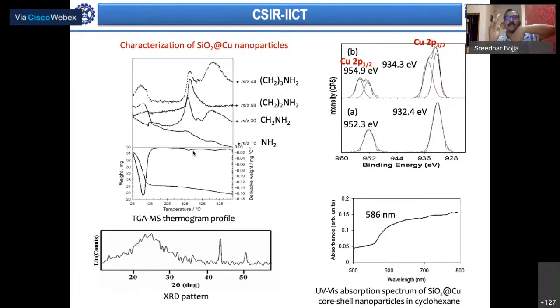All these fragments could be analyzed by coupling the TGA to a mass spectrometer. When this TGA was coupled to mass, whatever fragments got decomposed due to the functionalizing agent could be observed, giving us confirmation that the synthesized material has this functionalizing agent between the shell and the core. That is how we try to confirm it.